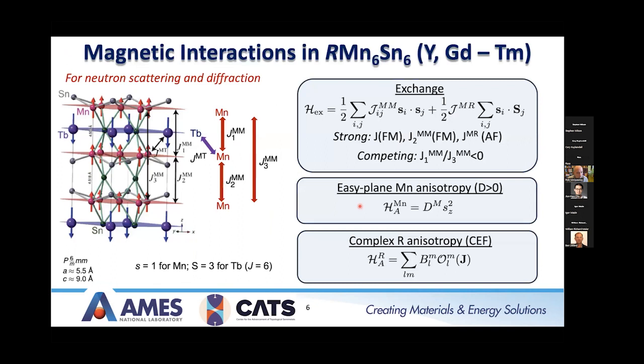All right, so getting back to the R166s. For our diffraction and inelastic scattering measurements, we've been using this Heisenberg Hamiltonian in a mean field approximation mainly. But right here we get the Heisenberg Hamiltonian. The main interactions are the intra-layer manganese exchange, which is strongly ferromagnetic.